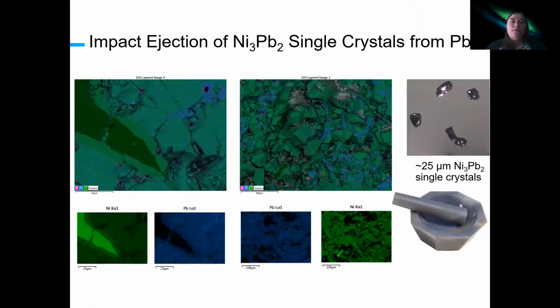So what I was able to do then is this pellet is very malleable. You are not able to grind this material. Lead is very similar to cold butter in texture. And so when you hit these pellets, you can actually eject the much more brittle crystals of the nickel 3 lead 2 out of the malleable pellet and end up with these beautiful single crystals here.